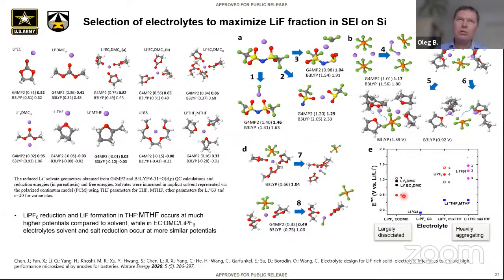They will go against the suggestion of Chunsheng Wang's group that we need to form as pure a LiF-based SEI as possible. So the next question is, what could be the solvents which would allow the large separation and preferential LiF formation? And PF6 is one of the best salts for that, because it has 6 fluorines to 1 phosphorus, right? So you do form a lot of LiF from 1 anion.